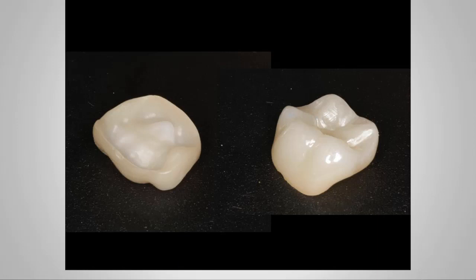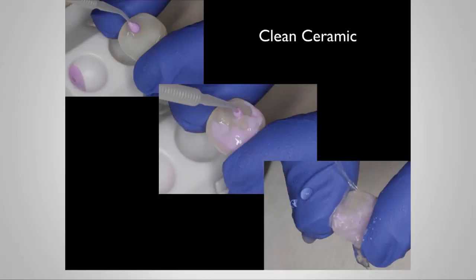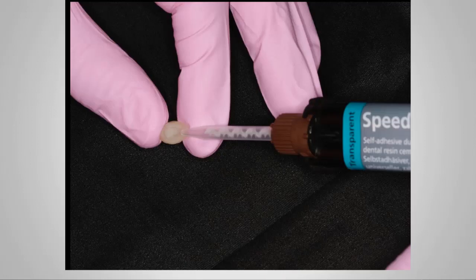This is a typical posterior zirconia crown, and if we're going to bond that, we're going to try it in, of course. It does contaminate the surface. The lab has already sandblasted that internal surface, so you get it sandblasted. Try it in, you contaminate it. We adjust it if we need to. Now we're going to go ahead and clean the surface. This is going to be the Ivoclean. We're going to let it react for 20 seconds and rinse it off.